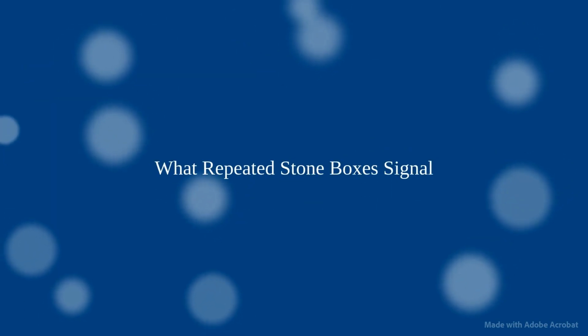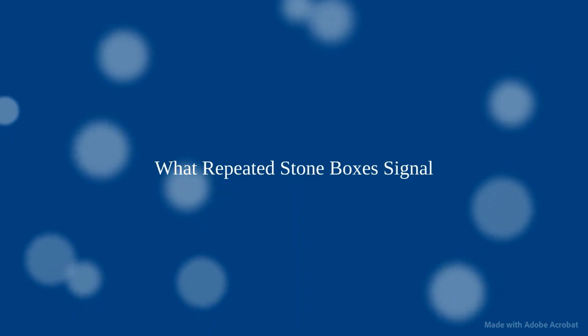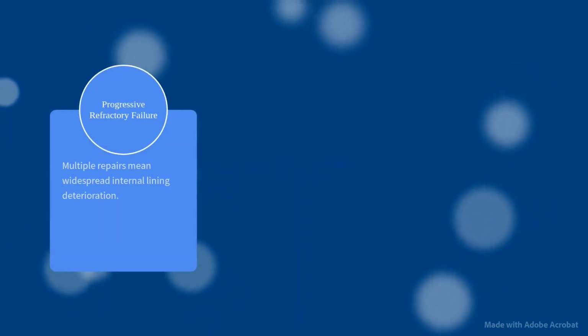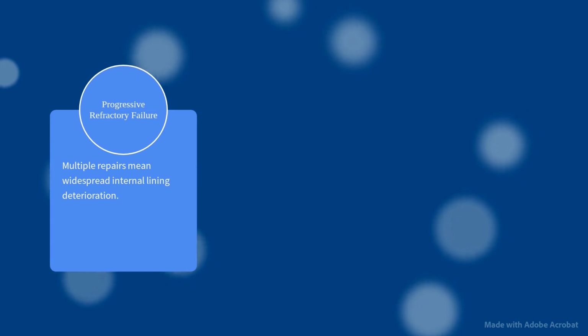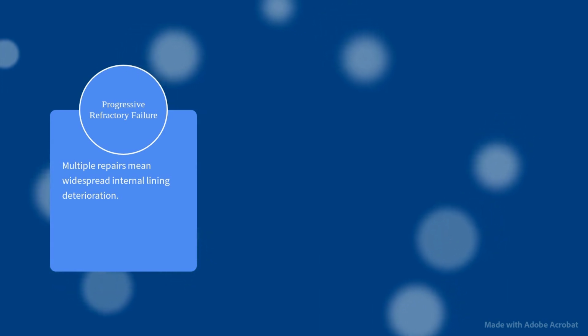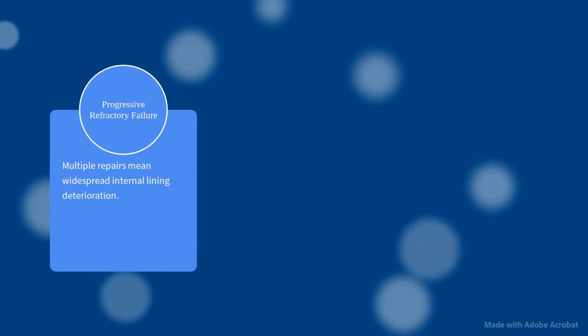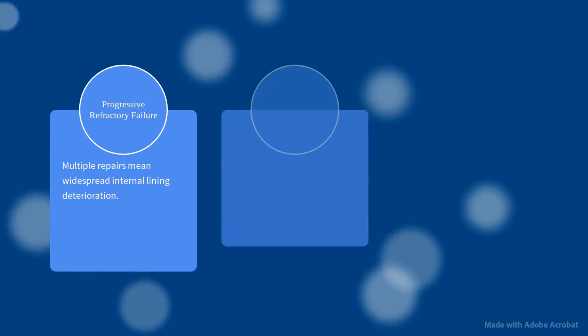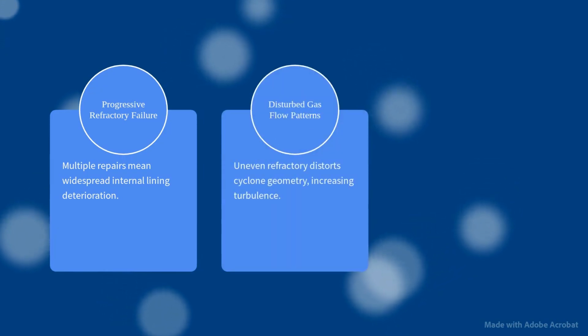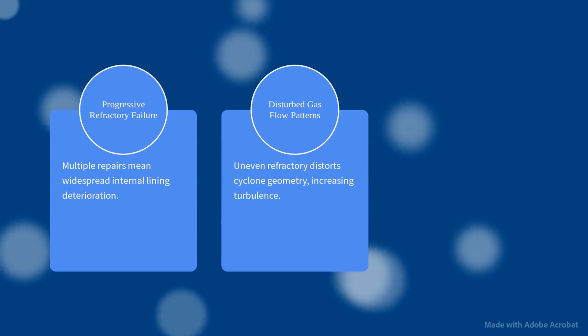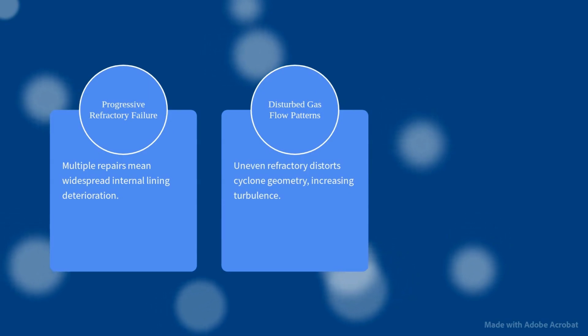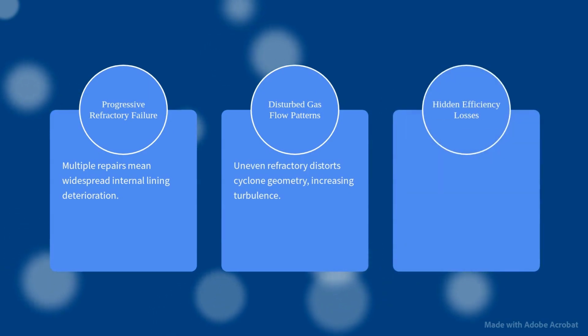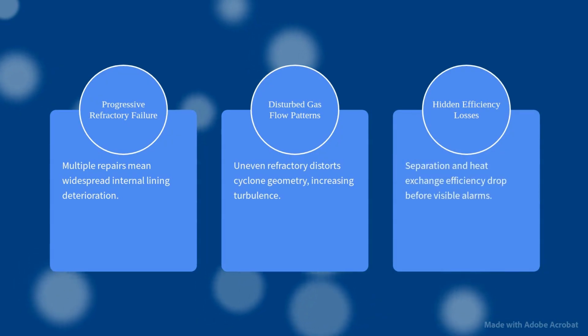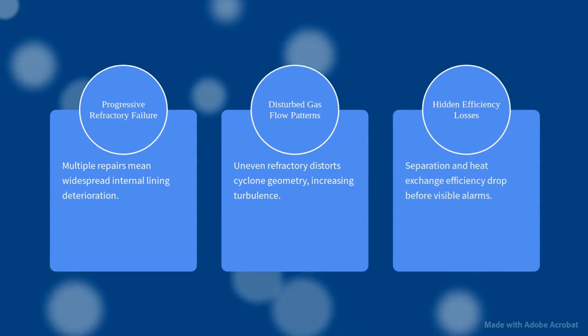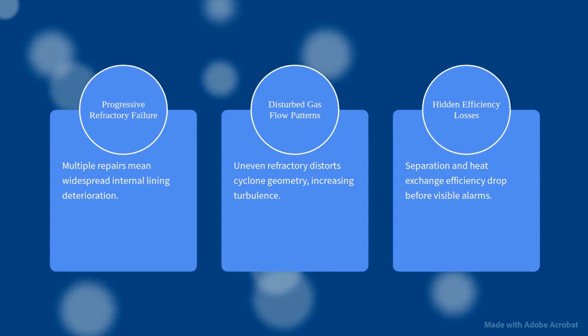Let's break down what repeated stone box installations are really telling us about the cyclone's internal condition. Progressive refractory failure is signaled by repeated stone box repairs. This means the internal lining is deteriorating across various cyclone areas. Disturbed gas flow patterns result from uneven refractory, which distorts the cyclone's geometry and increases turbulence. Hidden efficiency losses occur as separation and heat exchange efficiency decline, long before any visible alarms or production drops.